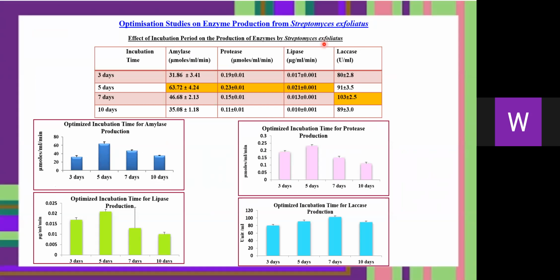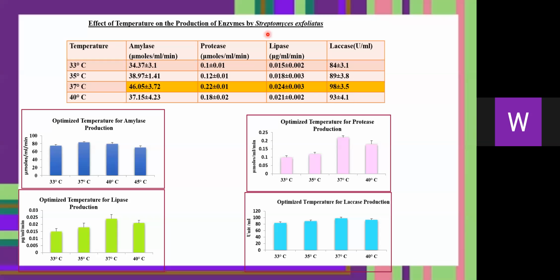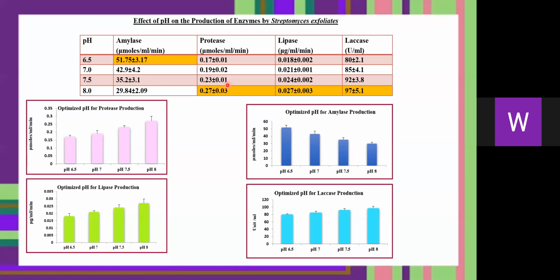Optimization of enzyme production from Streptomyces exfoliatus. It was observed that amylase, protease, and lipase are produced at maximum on the 5th day of incubation, whereas laccase showed its maximum enzyme production on the 7th day. Effect of temperature on production of enzymes: 37 degrees centigrade was the optimum temperature for maximum production of all 4 enzymes. Effect of pH: only amylase produces enzyme at the maximum at pH 6.5. Other than that, protease, lipase, and laccase produce their enzymes to the maximum at pH 8.